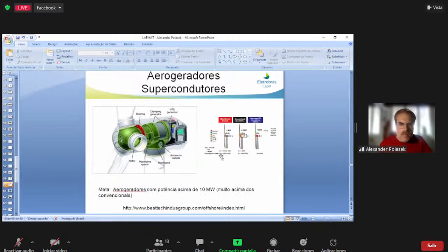And also, wind generators are another interesting field because it's quite challenging to achieve powers above 10 megawatts per wind generator. Typical commercial wind generators have a few megawatts of power, 2, 3, or a few megawatts. And if you have a superconducting generator, it's much lighter, and it's easier to have the structure. You have a lighter structure for the same size as the small power conventional one. You can increase the power without increasing the wind generator.